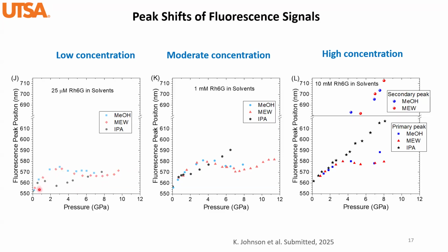So in the case of methanol and ethanol water, we always see a red shift, then a blue shift, and then a red shift as a function of pressure, and similar at higher concentrations. But in the case of IPA, we see a similar red shift, blue shift, and red shift at the lowest concentration. But when the concentration increases, we just see almost a constant red shift. And also here, this part just plots the redshift of the secondary emission peak.